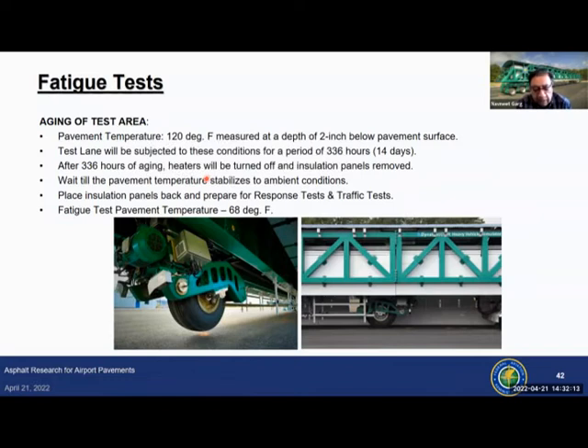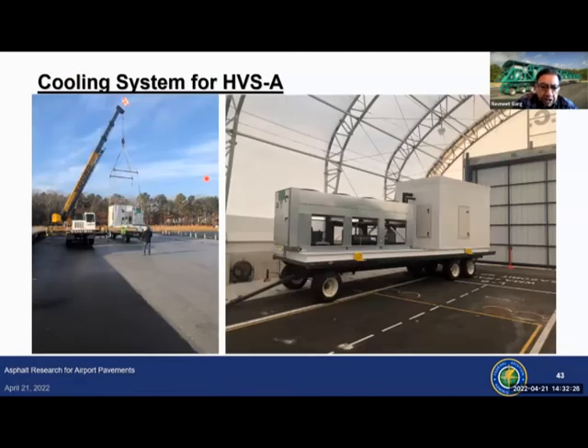And we are performing these fatigue tests at a pavement temperature of 68 degrees Fahrenheit, 2 inches below the pavement surface. So during winter months, we had to use our heating panels to maintain 68 degrees. But for summer months, we would need to cool down our pavement. So we acquired this cooling system that will be connected to HVS during summer months. So this cooling system can take pavement temperatures down to 50 degrees, 2 inches below pavement surface, and maintain the temperature when the outside temperature is up to 120 degrees.